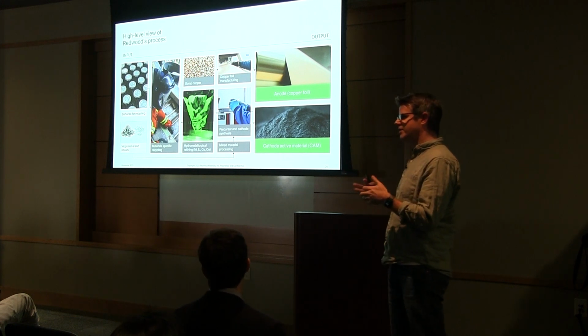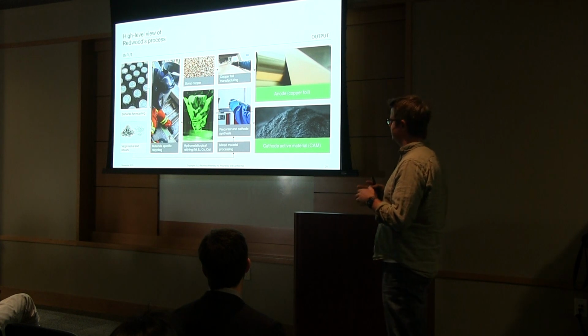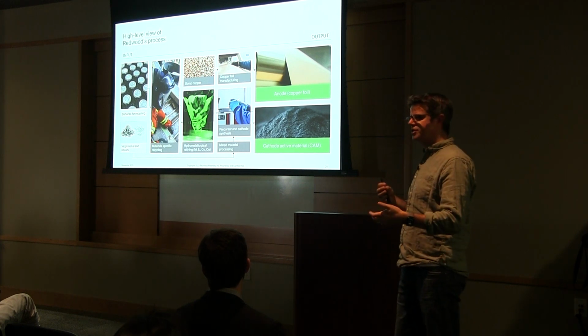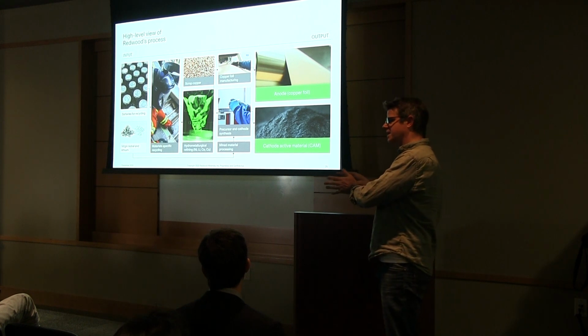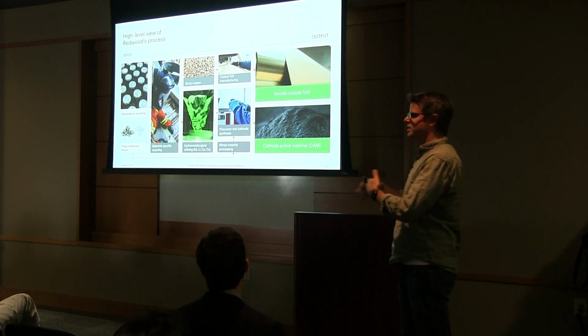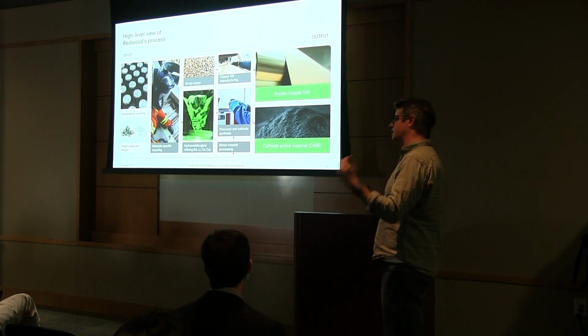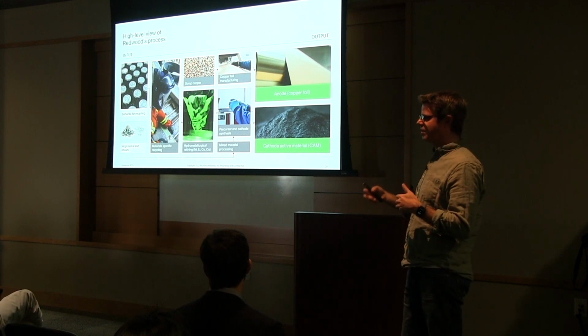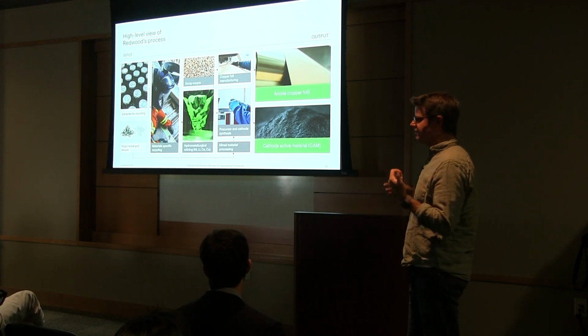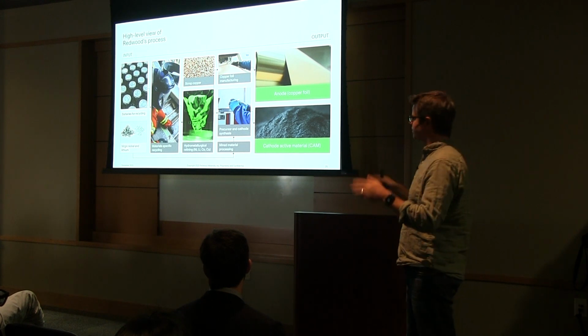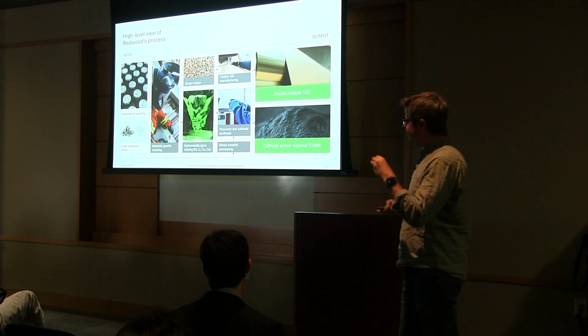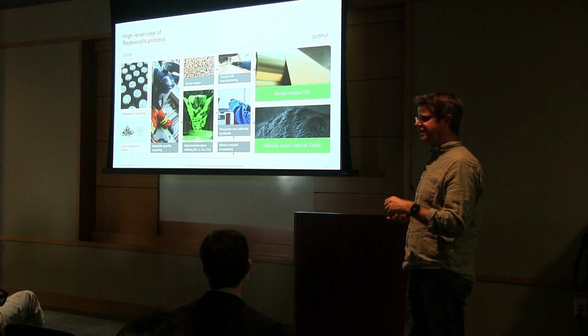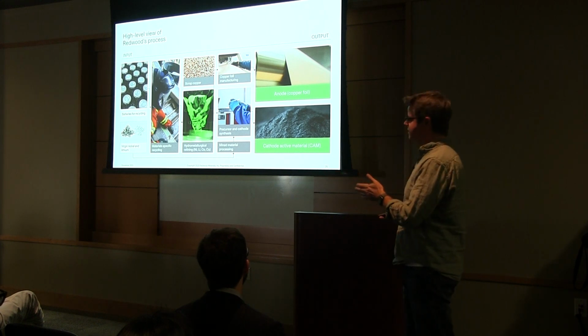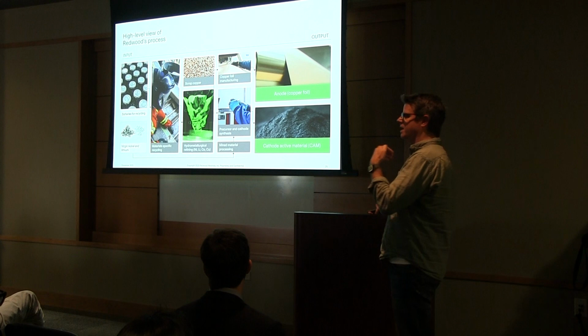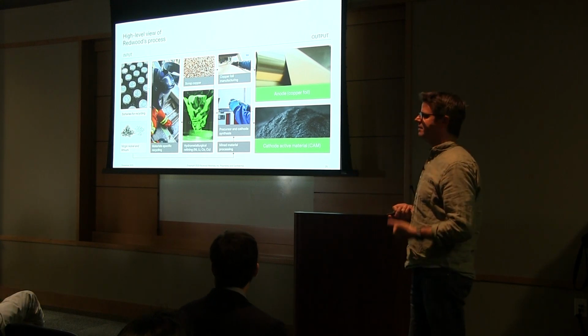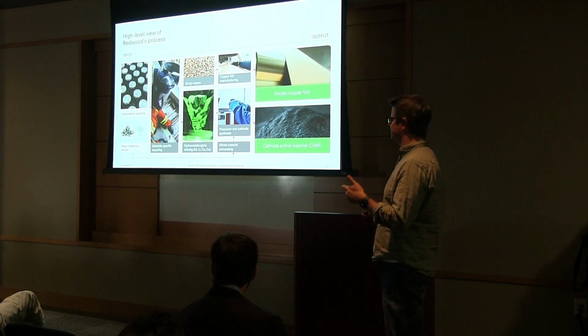In a thermal process, this is running at a moderate temperature, about 500 degrees Celsius, where we don't combust the graphite, and the idea here is to flash off the electrolyte. We then take that material, we call that calcined batteries. We pass that through a mechanical processing step to separate any copper foil, aluminum foil from the fine nickel cobalt graphite powders. Those oversized materials can be then split and sent to various recycling streams. The fine nickel, cobalt, graphite, lithium powder that comes out of that process is then sent through hydrometallurgical refining. So when it comes to live production scrap, we're looking at thermal processing, mechanical processing, followed by hydrometallurgical processing.